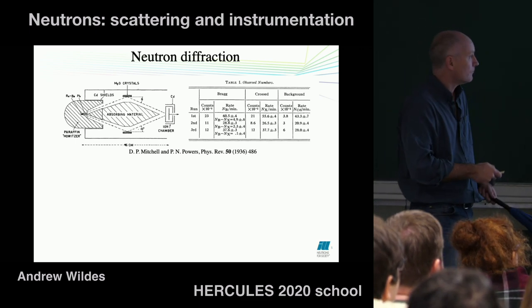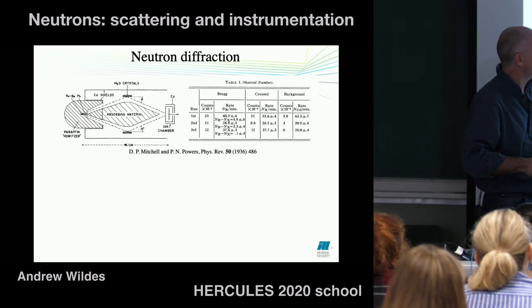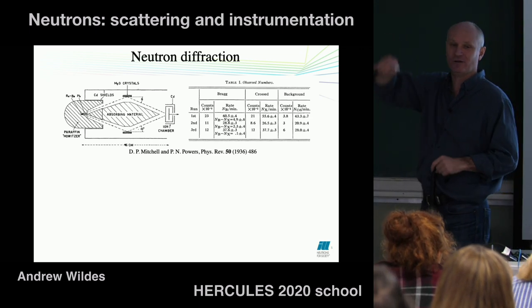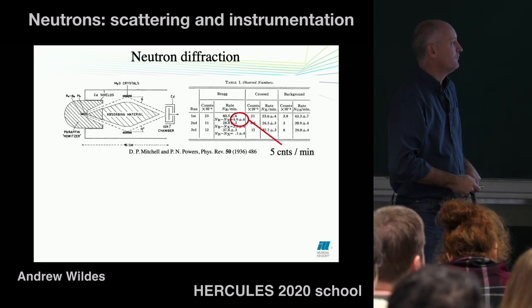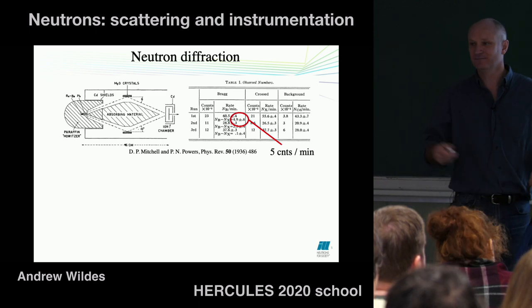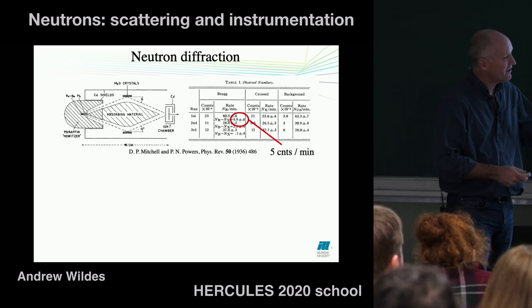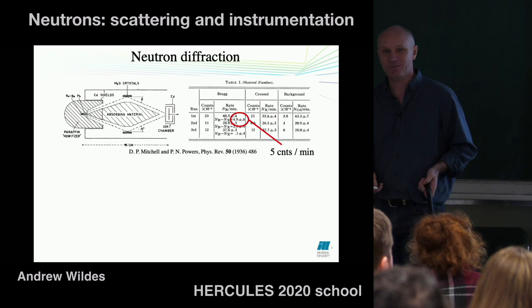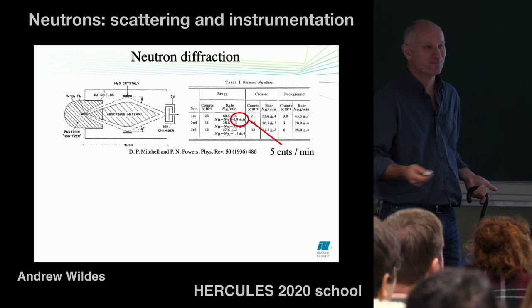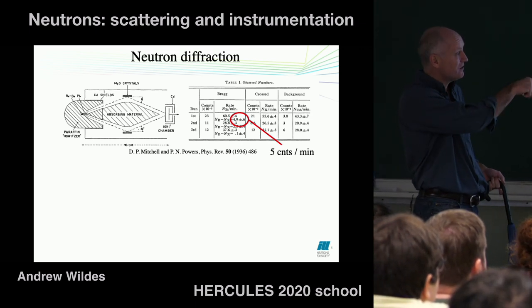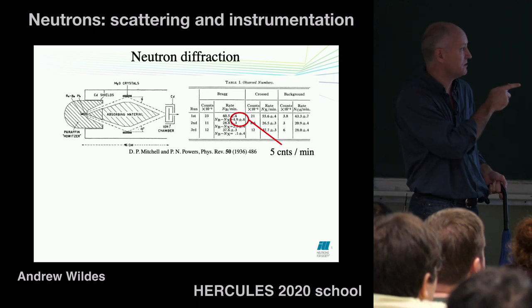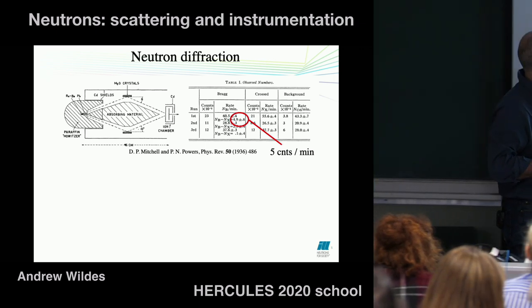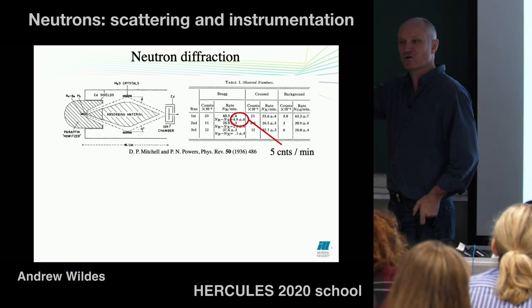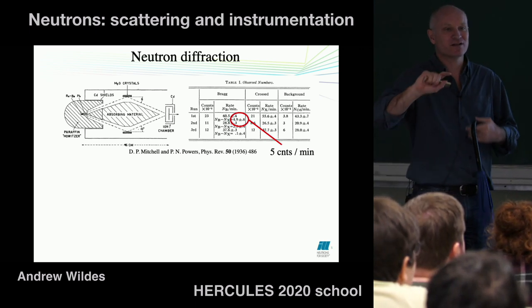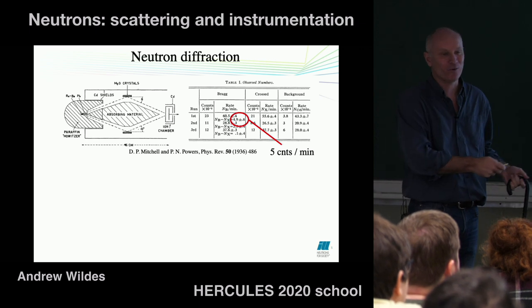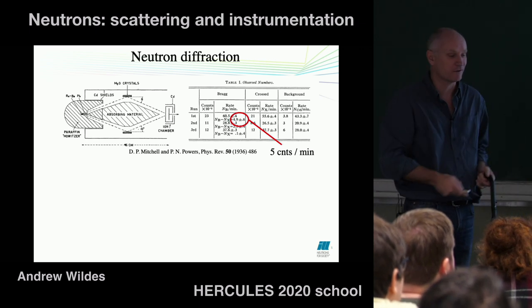And it worked. So this number here, if you look closer, you'll see NB minus NX. NB is at the Bragg angle, NX is when they're turned off. And if you look at the number of counts, 5 counts per minute. That's how they were counting. So you can imagine if you wanted 10,000 counts in that, you'd be there for a very long period of time indeed. And that was the best. They did a bunch of these experiments. That was the best statistics they got. And if you look carefully, they've even put the error bars on this. This is 5 plus or minus 0.6. So it's of the order of 10% error on what they got there. But it was good enough for them to say it worked.